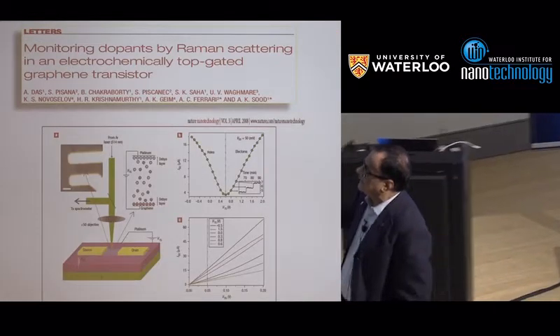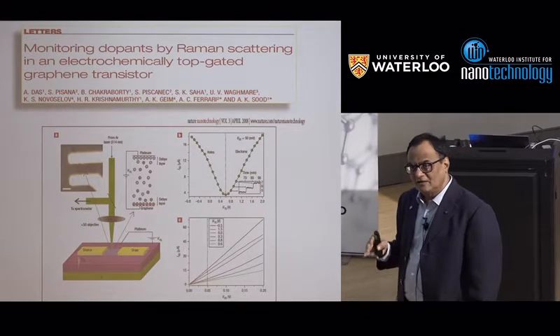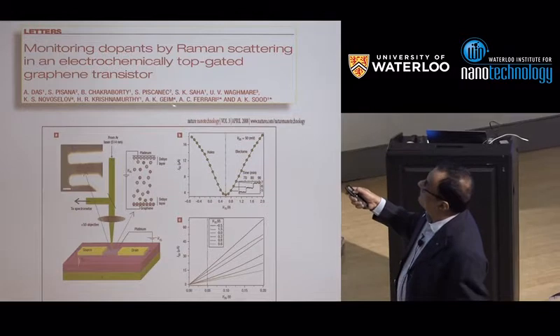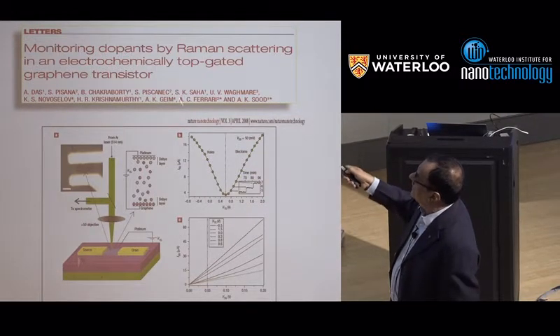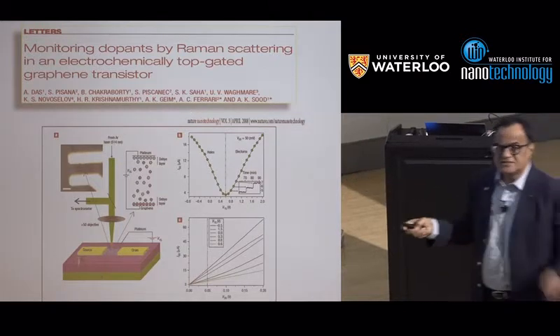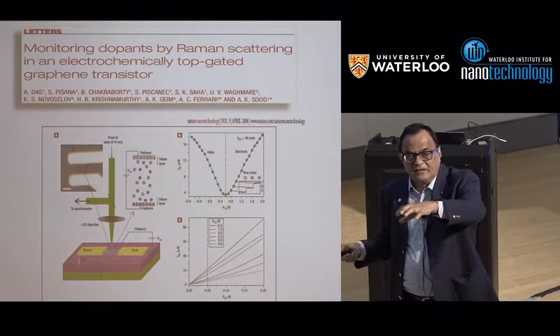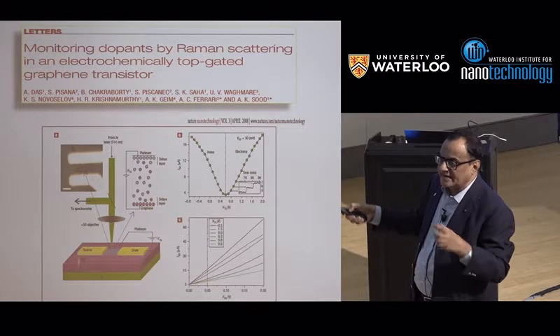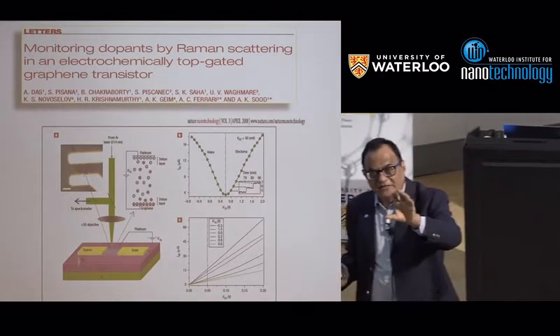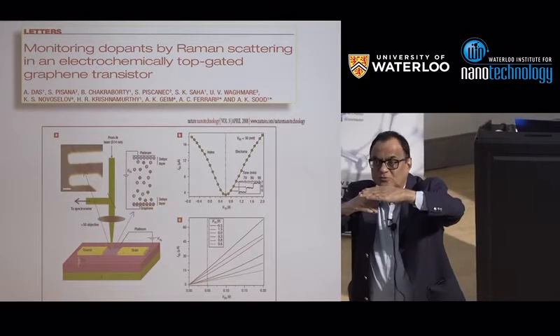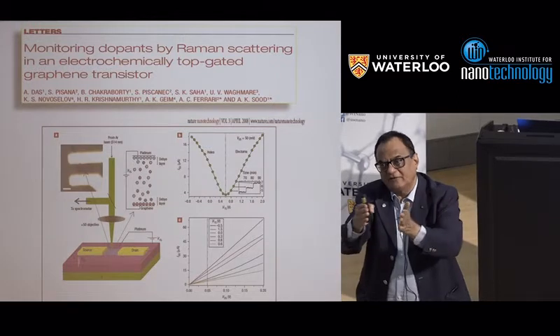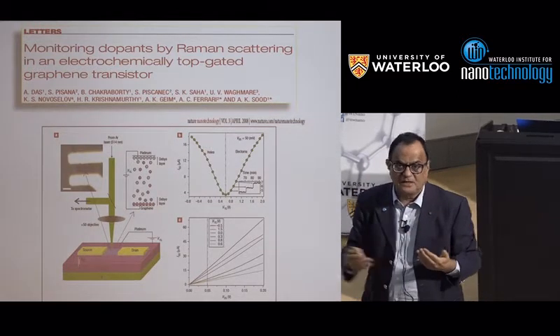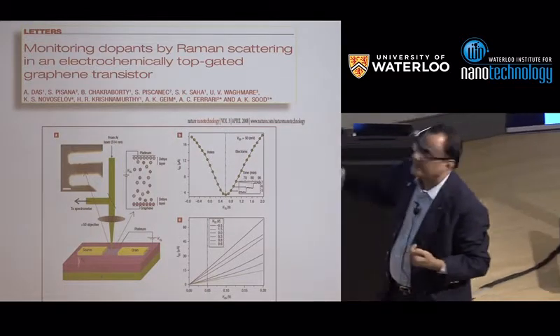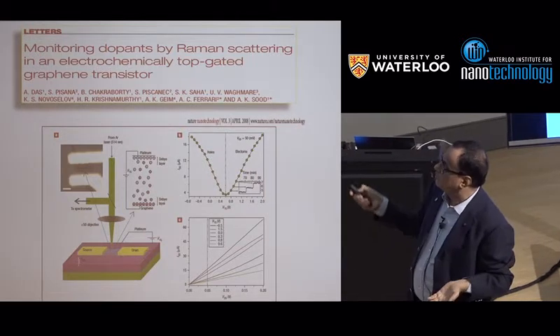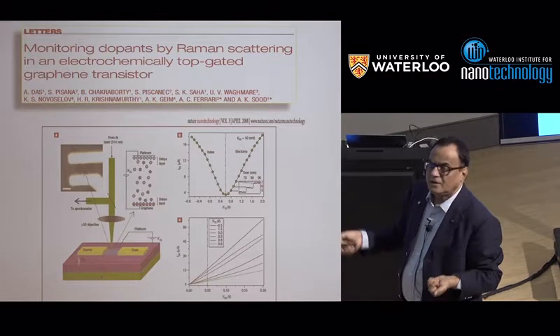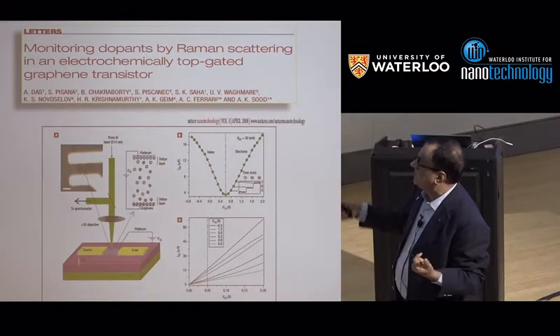Now, what we did at that time, this is 2008, when we were really not making our own devices. The devices came from Andre Geim and Novoselov and through Cambridge, and we made these devices, and instead of a back gate, we put the top gate electrochemically. So we have an electrolyte and a platinum wire which acts like a gate. So the double layer, which is only 1 nanometer, replaces 300 nanometer of SiO2. So whatever you can get with 100 volts, now you can get with half a volt. And you can get very large doping of the devices, electron or hole, and you can really show that it's a beautiful electrochemical transistor. Now what we do, we put this device in the Raman microscope and look at the Raman signatures as a function of gate voltage. And that is very interesting.